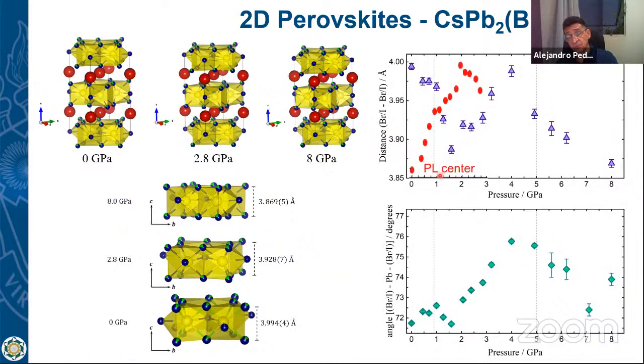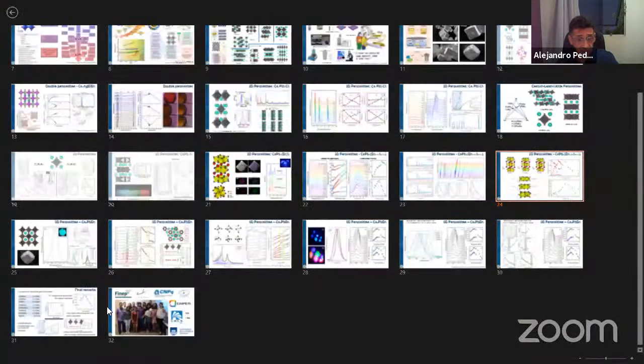And when we compare this with the photoluminescence, you can see that when the photoluminescence changes, there is in fact a change in the bromine octahedra. So the changes in the luminescence are directly related to how the octahedra change. This change will change the energy level of the excitons, which lie inside of this octahedra, and these excitons are those which produce the luminescence. So I will go directly to the end of my talk with that.